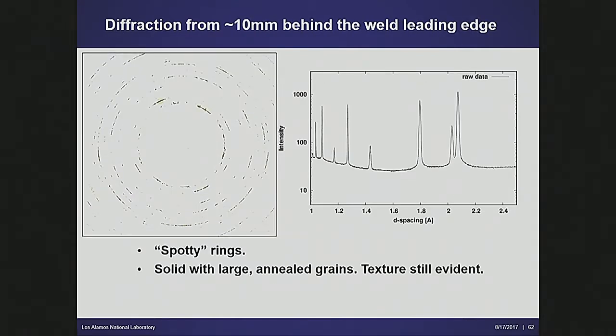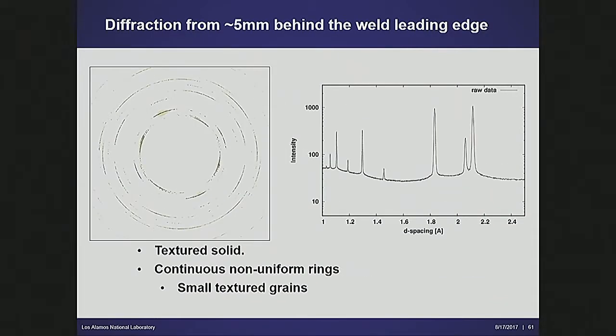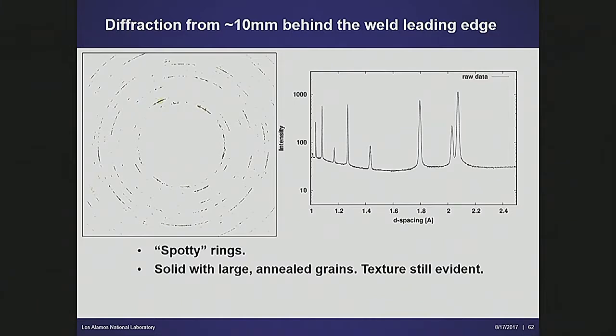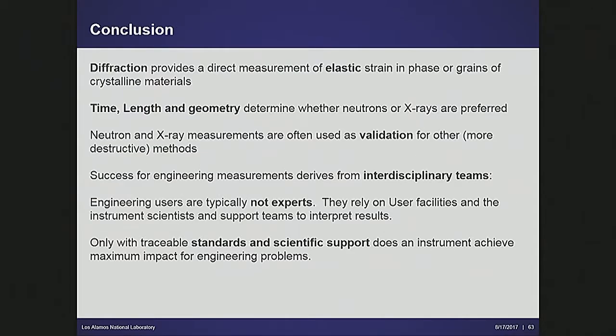And then when you go all the way back out here to 10 millimeters behind the weld, you can see that the rings have become very spotty, right? Still got some gaps. It's qualitatively different from this, right? And from that, you can infer that you probably got large and annealed grains, right? You've done all of this in a few seconds after the welding process, right? And then you can relate this to offline characterization after the fact. But hopefully you can see the power of doing this.